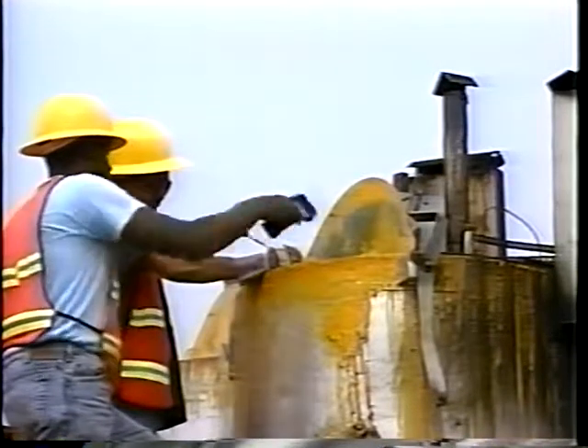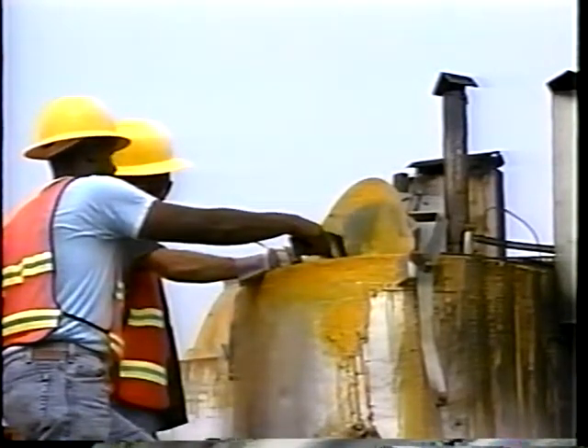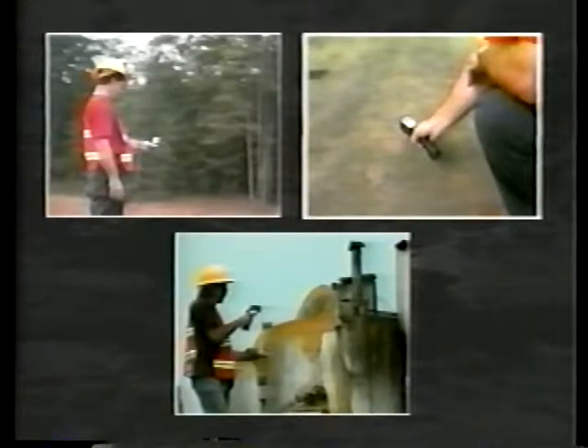To ensure proper heating, check all material temperature gauges daily against a calibrated thermometer for accuracy. Measurements should be taken every 2 hours or less. Record ambient air, pavement surface, and marking material temperatures at the time of application and store in the project files.